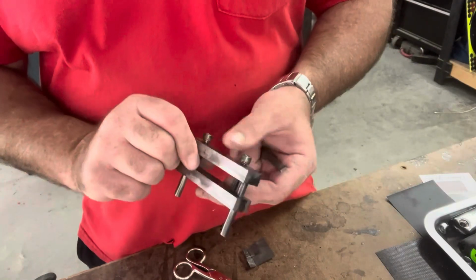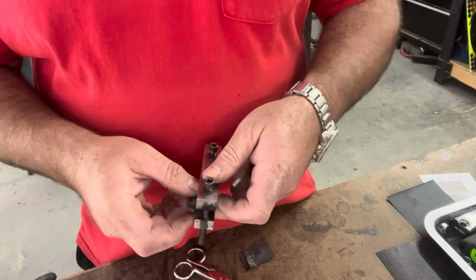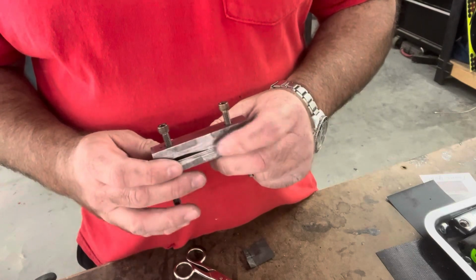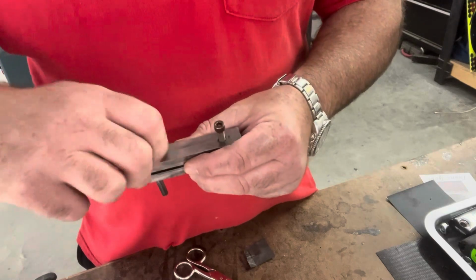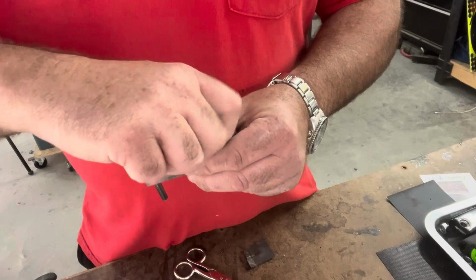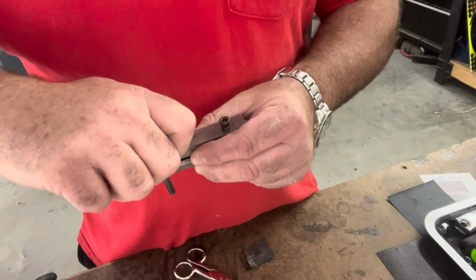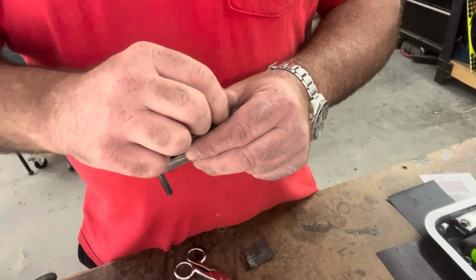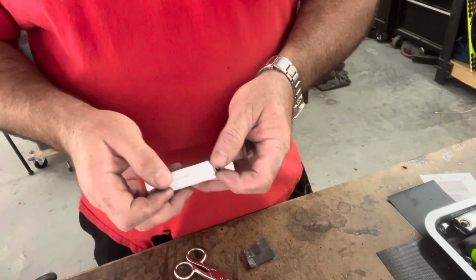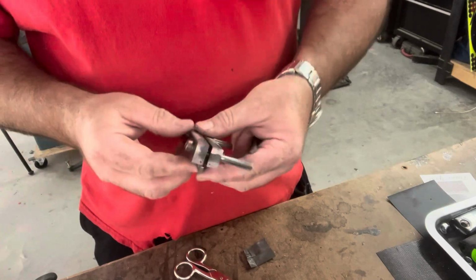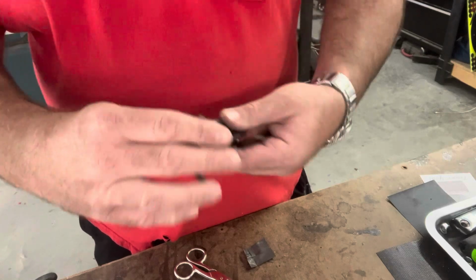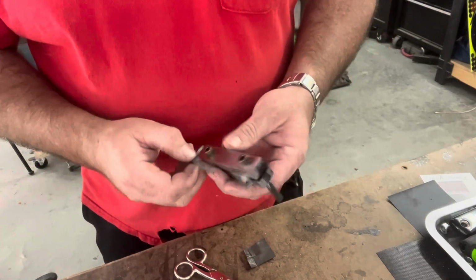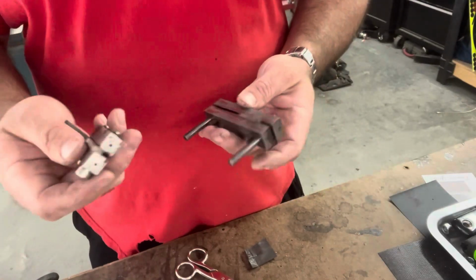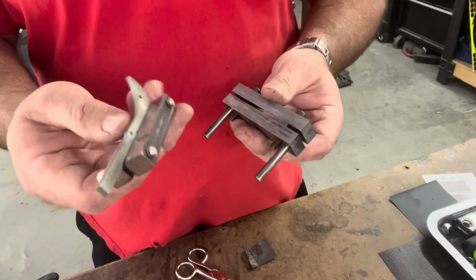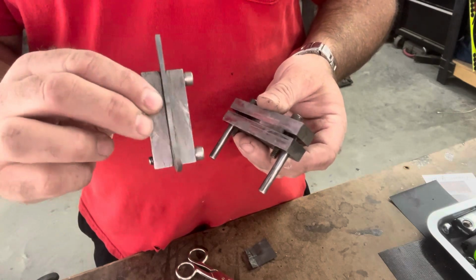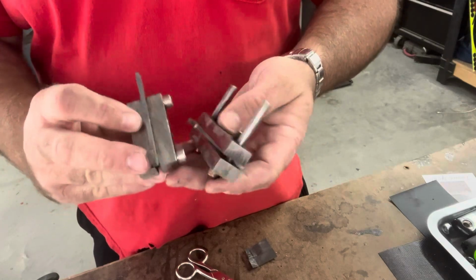Alright, now my blade, I'm actually going to clamp it into this file guide, because it's a pretty good size file guide, just for safety issues on warpage inside of the freezer. I'm going to put this in a Ziploc bag, put it in my freezer for about a couple of hours, and then bring it out and temper it. Don't want to pick up a warp. I've actually got 2 file guides that I've made, and I'm going to use the smaller one for the spring to keep it from getting a possible warp in it, and the bigger one for the blade. I'm going to put these in a Ziploc bag, put them in the freezer.